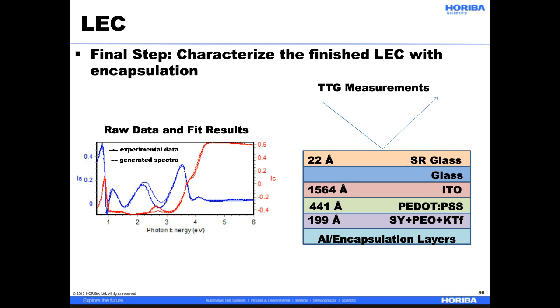Finally, we want to characterize the entire LEC with the encapsulation. We run into some problems here where we can't exactly measure from the super yellow side because the aluminum is completely absorbing. The encapsulation layers are, of course, on top of the aluminum, and they don't help with the measurement either. So what we can do here is actually flip the sample upside down and measure through the glass.